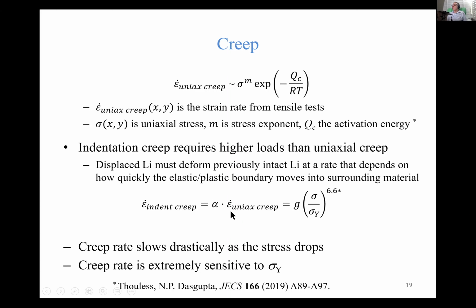So when we put in all the constants, we get that the indentation creep is some function of the ratio of the local contact stress and the local yield stress, and that's raised to the 6.6 power. That's Dasgupta's number, and other people have gotten very similar numbers. Now, this is a very, very large exponent. What that means is as the